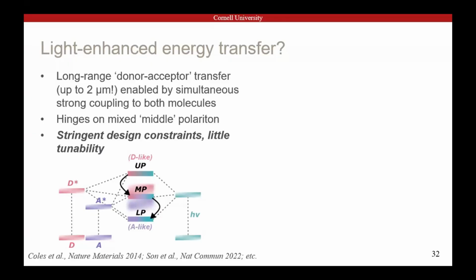And then when you think of it this way, in the cavity, when you photoexcite an upper polariton, you're just getting relaxation down this polariton manifold. And it eventually leaks out of the bottom state. But the bigger challenge is, while this has been seen many times, this is a really hard system to set up, because you have to carefully balance the donor-acceptor strengths, the relative energies. There are basically no knobs you can turn. And we like to turn knobs in my lab.